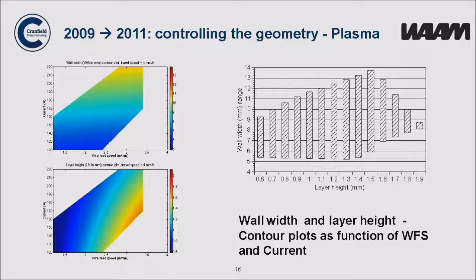Now, when you're building additive manufacture parts using WAAM, the layer height is never what you want it to be. It always changes and it varies around the part. So you have to correct this every layer. And the only way you can do that is if you have a full detailed algorithm. So if the layer height ends up being 1.1 millimeters, on the next layer you build it with 0.9 millimeters.